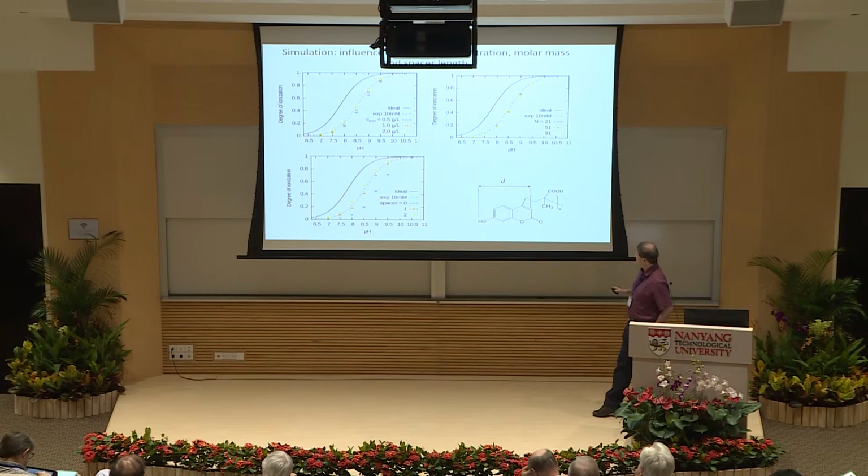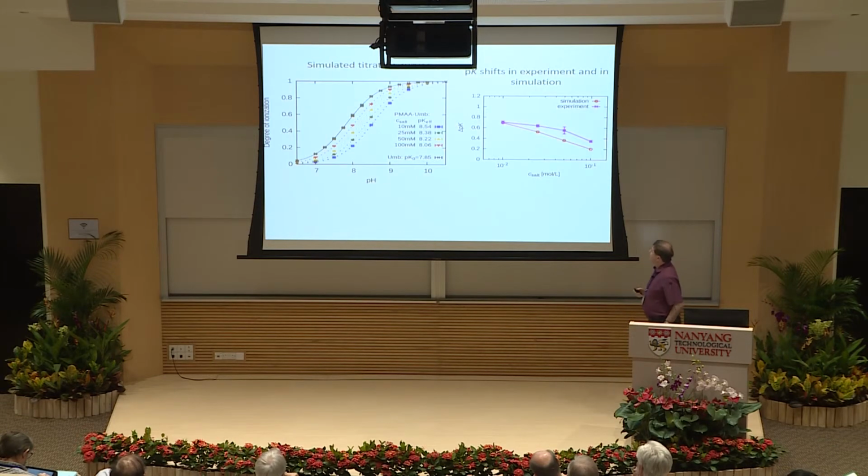So for comparing the experimental data with the simulation, this spacer length must be set properly in accordance with the actual length of this fluorophore. And if we do so, we can obtain the titration curves from the simulation, and we can compare them with the pK shifts from the experiment. Again, the match is not perfect, but in both cases, we are able to see the shift of the pK affected by the electrostatic screening of the added salt.